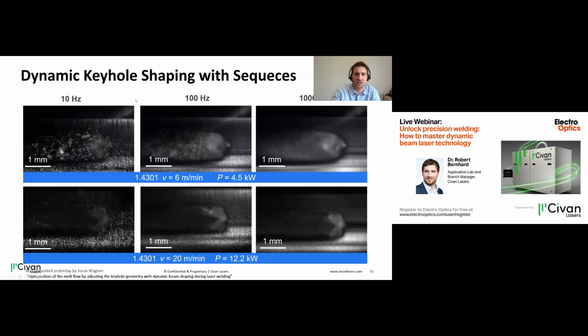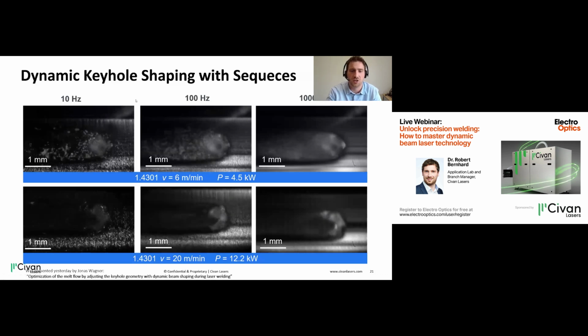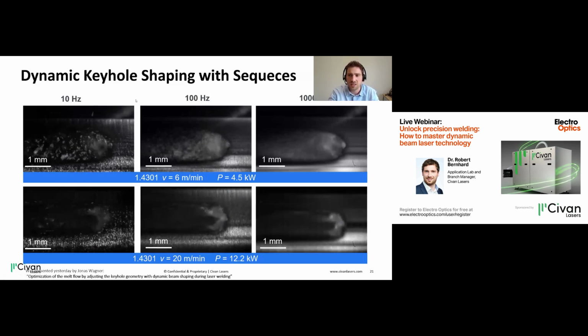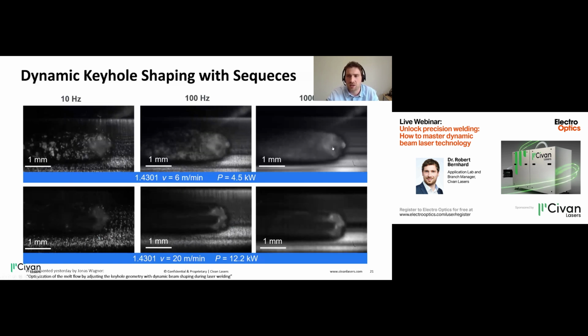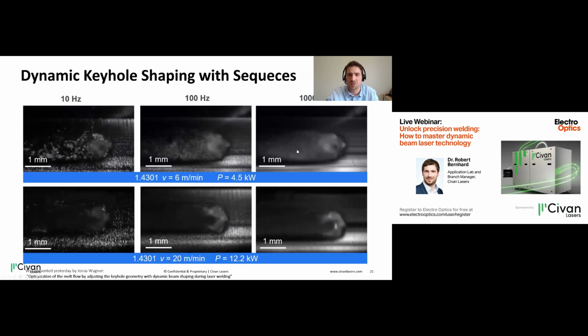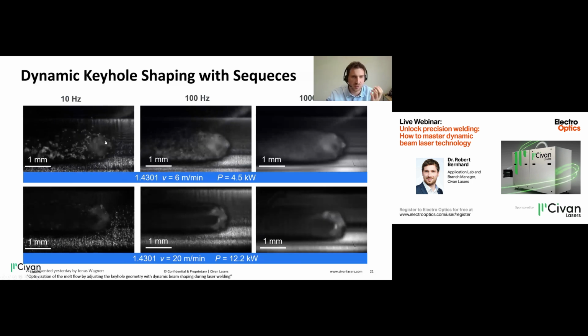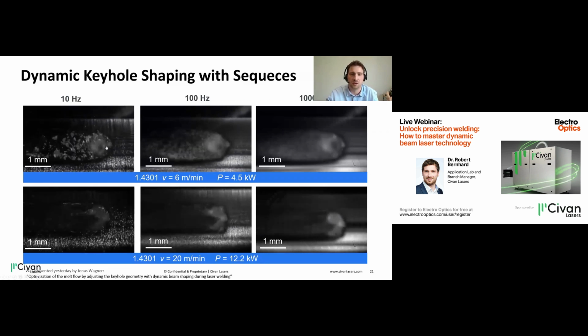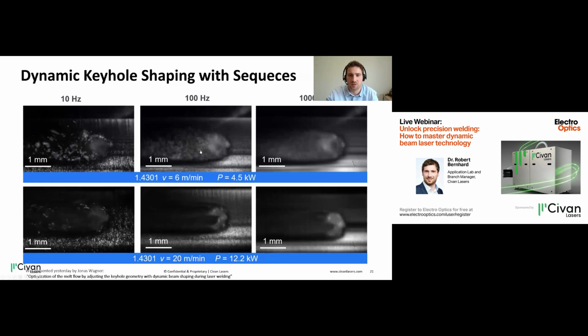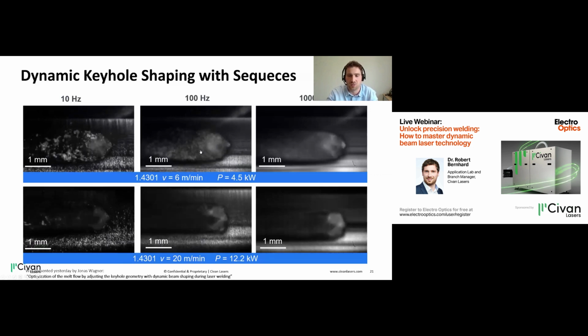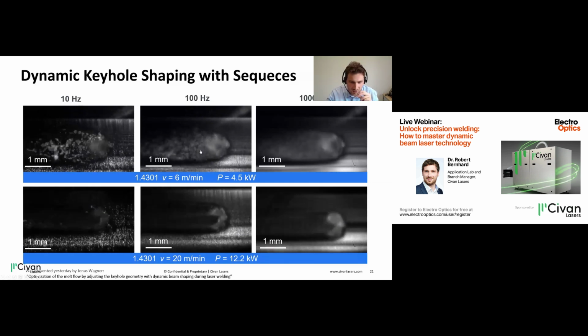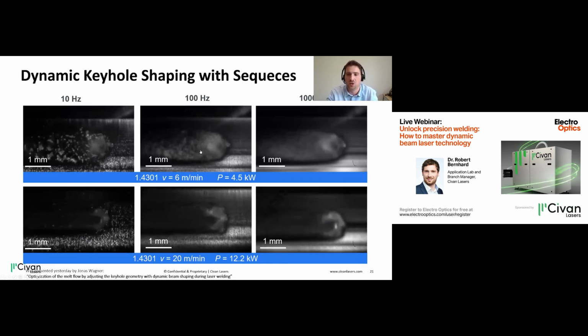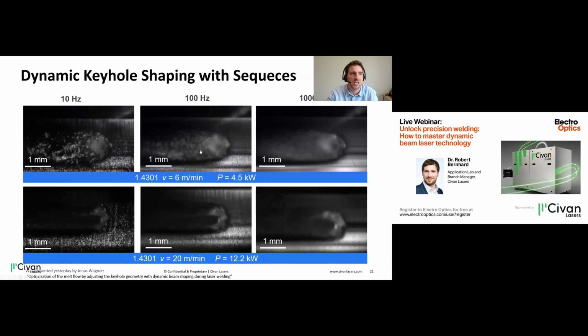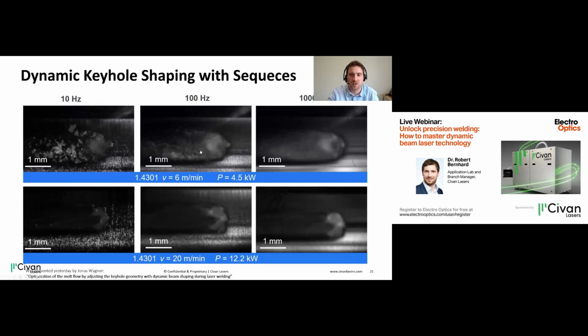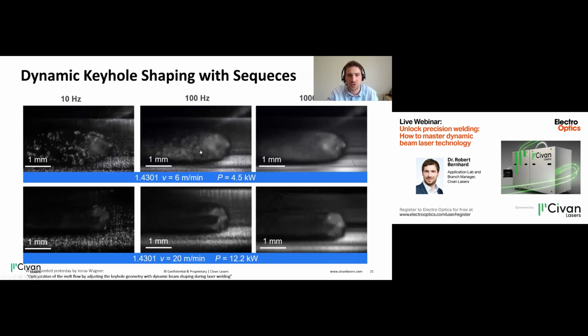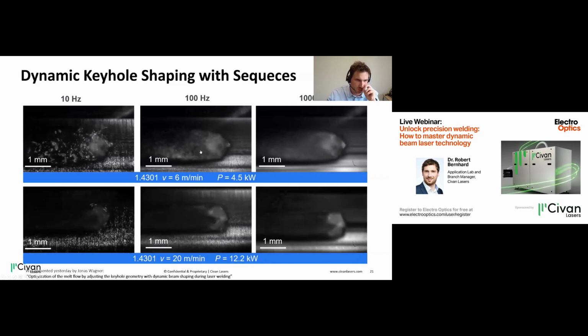And to see this in action, again, some nice high-speed footage on some stainless steel. Here you can actually see the flipping and the change of the beam shape at different frequencies, which means different times, how long they are visible and for how long they do something. And this is here just to illustrate that we're actually able to get the beam and the melt pool motion just right to get a very smooth and calm process and actually reduce pores and spatter.